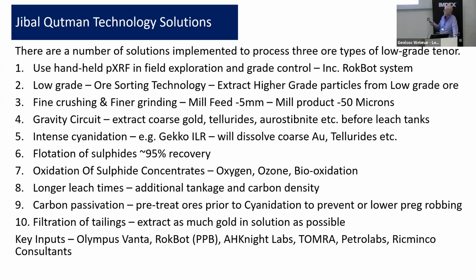Gravity circuit is very important to take out the coarse gold and the tellurides. Tellurides, as I mentioned earlier, are very slow leaching. So if you can get them out early days, you can put them into intensive cyanidation, which will actually recover the gold from the tellurides. If you leave it in circuit, you'll be lucky to get 50% before it goes through the tailings. And that, again, this Gecko inline leach reactor is one of probably the best on the market.